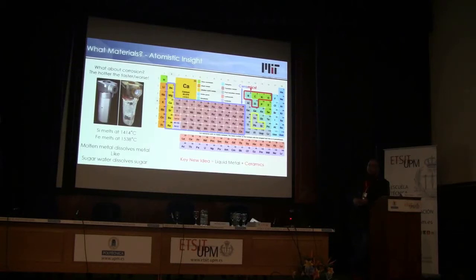This has an interesting effect on corrosion, because when you go really, really hot, let's say you start with silicon and you have some impurities in the silicon. Those impurities won't be able to form any corrosive byproducts, because none of those byproducts are stable enough to stay solid at those temperatures once you get that hot. And so you can push high enough in temperature that you get to a new regime where it's difficult for things to corrode and form new compounds.